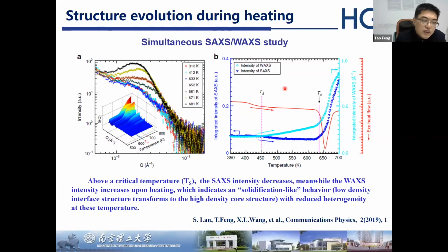And we first reported this polyamorphous phase transformation in the nanoglass. You can see from this curve, above a critical temperature Ts, the SAXS intensity decreases, and meanwhile the WAXS intensity increases upon heating. So this indicates a solidification-like behavior happens. What does this mean? This means this low density interface structure transforms to the high density core structures, so with reduced heterogeneity at these temperatures.